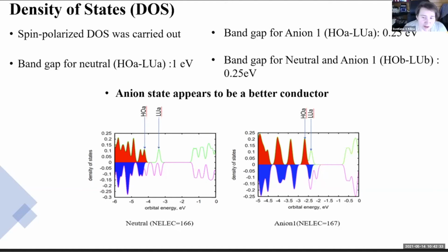Yeah. And the same would be true for your copper 2+. It looks like they're pretty much the same energy, up and down. Unoccupied levels are the same energy, or at least at this resolution it's hard to say. But you need to take the gap with the occupied beta state, because the highest occupied state now corresponds to spin down. Right, LUMO alpha minus HOMO beta. Or maybe also LUMO beta, because it's really hard to say. No. In VASP, they always populate alpha with more spins than beta. It's just a convention.